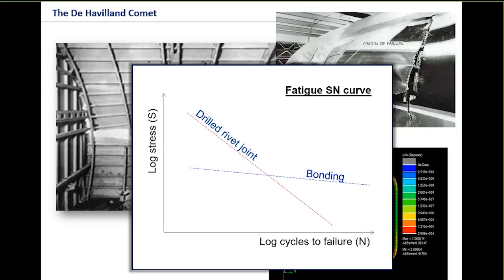Now what we find is if we've got a bonded joint, it's a bit like a binary one. If you drop the stresses low, it almost never fails through fatigue at all. But once the stresses get above a critical amount, then it will fail almost instantly. So it's a very shallow SN curve, very long lives at lower stresses, but just raise the stress above that critical level and it fails catastrophically.